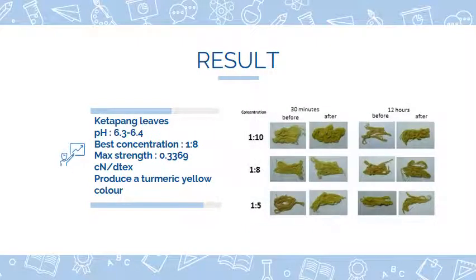The result of dyeing the threads with the colored pigment from ketapang leaves gives a turmeric yellow color. This yellow pigment appears due to the carotenoid content in ketapang leaves. In the 30 minutes immersion treatment, the yarn produced a golden yellow color for 1/10 and 1/8 concentration, while the 1/5 concentration produced a turmeric yellow color before fixation.